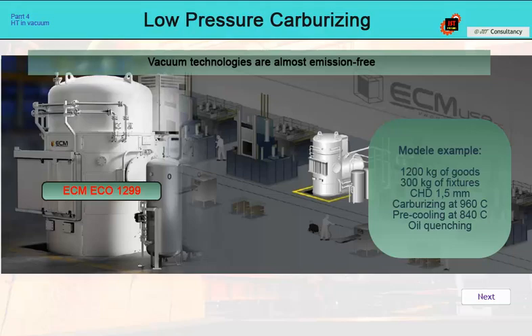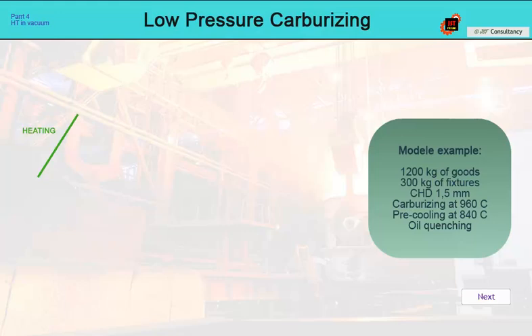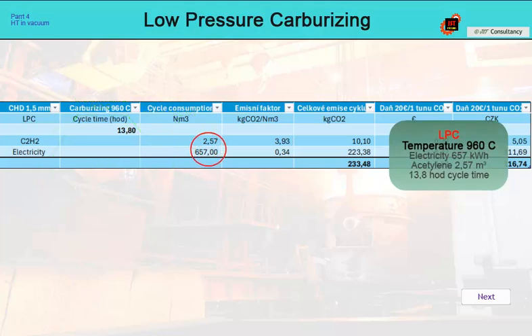The model process consists of heating to the carburizing temperature, then the carburizing itself at 960 degrees Celsius, cooling to the quenching temperature of 840 degrees Celsius and quenching in oil. The total electricity consumption is 657 kilowatt-hours and 2.57 cubic meters of acetylene. The process time is 13.8 hours. The emission factor for acetylene is 3.93 kilograms of CO2 per cubic meter of gas. The emission factor for electricity is 0.34 kilograms of CO2 per kilowatt-hour. So we will have 233.48 kilograms of CO2 per process.